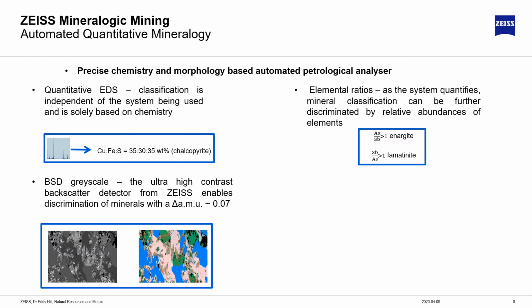We can't, with EDS, obviously analyze for hydrogen, or maybe a carbonate. And since we carbon coat, we're not analyzing for the carbon itself. And so perhaps something like a goethite and a siderite may seem similar in composition, since we're ignoring the chemistry and the water in one of them, and the other. But the gray level will then also help us discriminate between them. And so we can precisely classify them both.